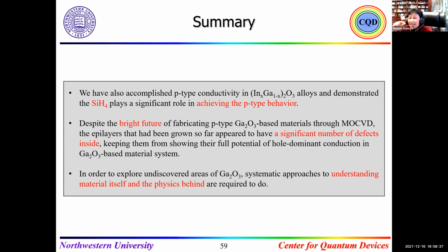So you don't need the thick layer, and as it's thin, in this case, the dislocation can be really very low. But I have a solution for you for the dislocation, similar to all of the other III-V aluminum nitride, gallium nitride, by doing the superlattice, thin superlattice of the indium oxide, gallium oxide.